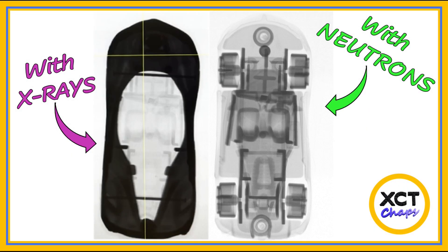This is because these plastic parts are abundant in hydrogen, which is highly attenuating to the neutrons. Whereas the metal outer body of the car is now barely visible. This is almost exactly the opposite of what we see with x-rays, where by the time we get through the metal pieces, we see them just fine, but we can now no longer see the plastics.